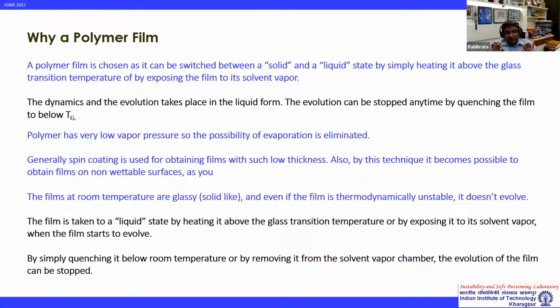So you now have an ultra-thin film in a liquid state, so the film can evolve, right? And polymer has a very low vapor pressure, so the possibility of evaporation is also eliminated. One of the key problems of working with a regular liquid is that there will be evaporation, and since thickness is a very important criterion in this whole physics, there will be a constant change in the film thickness, and scientific quantification becomes extremely difficult, right?